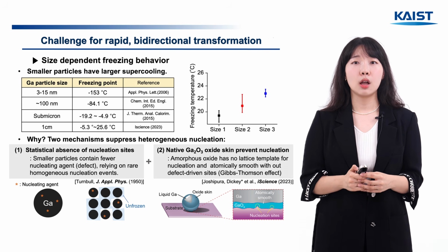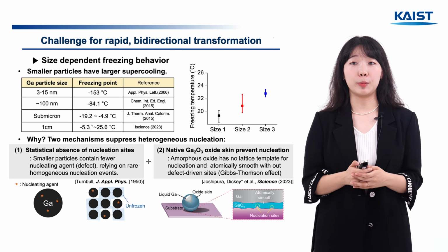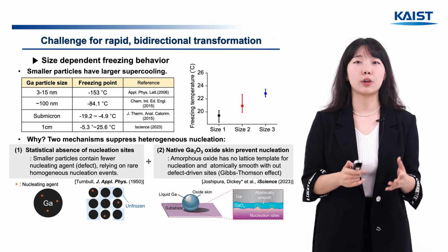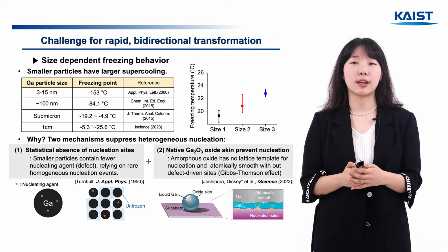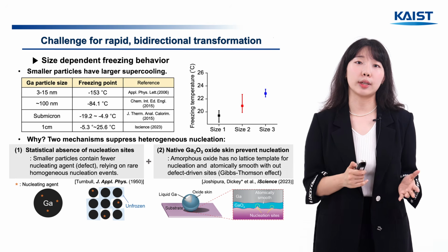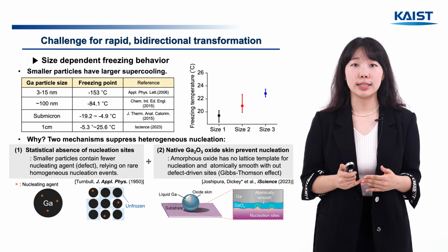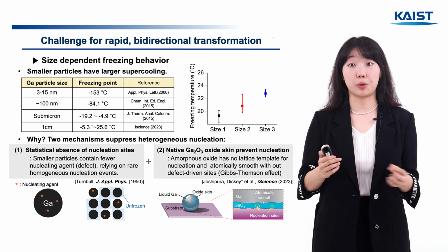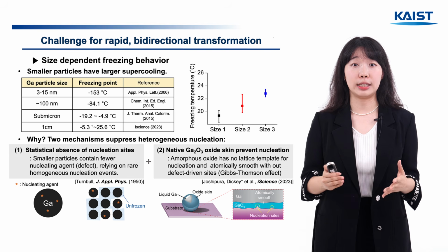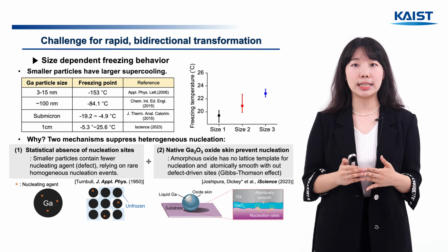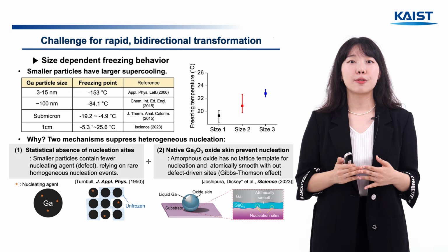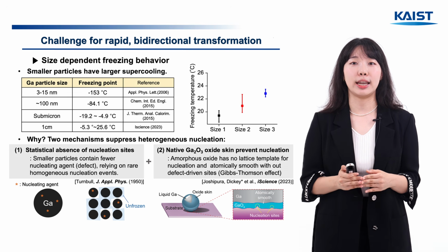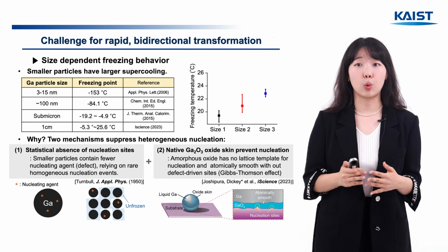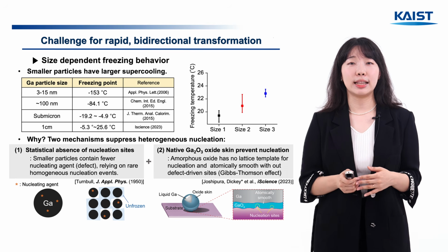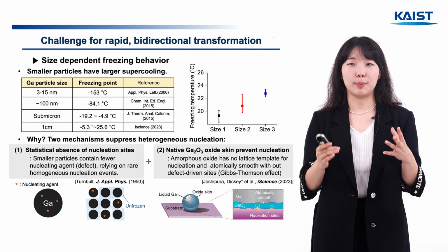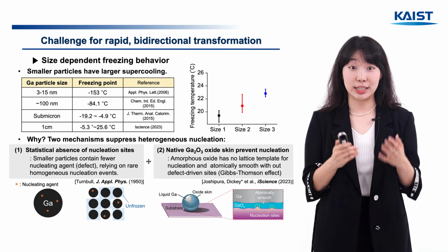The smaller the particle, the stronger the supercooling. Many papers report that smaller particles have lower freezing points, and our own experiments confirmed it. Smaller sizes froze at lower temperatures. When gallium freezes, it forms an alpha phase or a beta phase or others, but both have very high activation energy barriers, so gallium cannot easily freeze on its own. Instead, freezing usually has to be triggered by a nucleation catalyst, like an external defect or an impurity. The reason is that the smaller the particle, the lower the probability that such a catalyst is present inside.